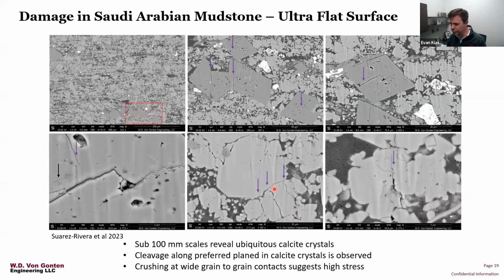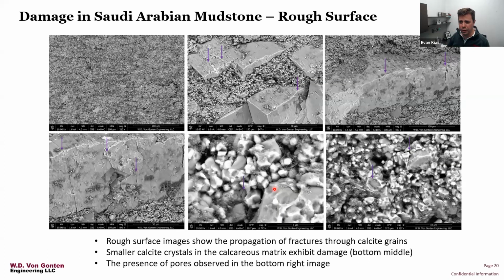And so, of course, we do see a lot of damage within the sample post-test. However, a nice way to look at it is that with these rough images, you can get a three-dimensional perspective on those fractures propagating through the calcite grains.